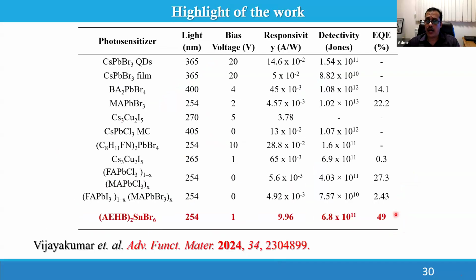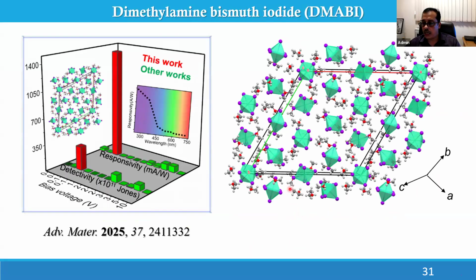And at that time, that means 2024, we were getting some very close to the state of the art with 10 to the power of 11 Jones detectivity and 9 ampere per watt. Earlier in the beginning, we were getting milliampere per watt. Now we got 3 to 4 order higher, and an external quantum efficiency of 49. That is good at that time. And we broke that values in the next work, that is another work we published in Advanced Materials this year.